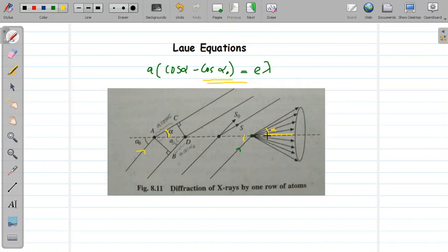So in fact we have a cone shape or a concentric cone with respect to the line of atoms, having a semi-apex angle alpha, and the diffracted beam falling onto this cone will actually have alpha as the scattering angle. So all these beams falling onto this cone can give us a diffraction pattern.